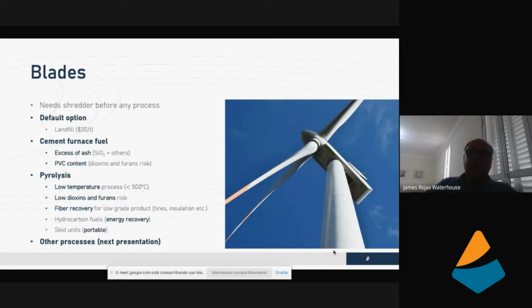So the other process is pyrolysis. Just put the parts of the blades into a vacuum chamber and heat up to around 500 degrees. You cannot heat up above 500 degrees, because you start to form a lot of hazardous materials also, and you'll start to form dioxins and furans again and other things. So you have to keep the temperature quite low, and the process takes quite a long time to vaporize, to gasify the whole plastic content.